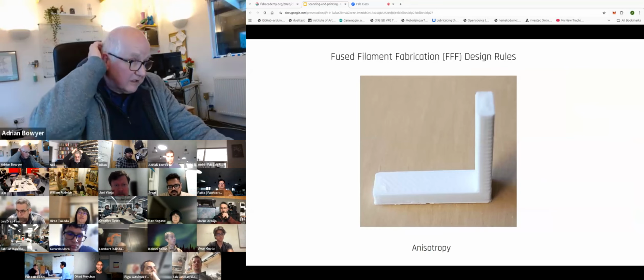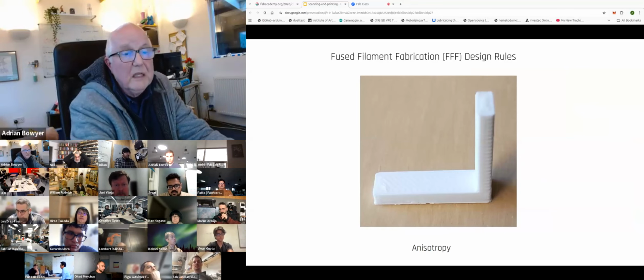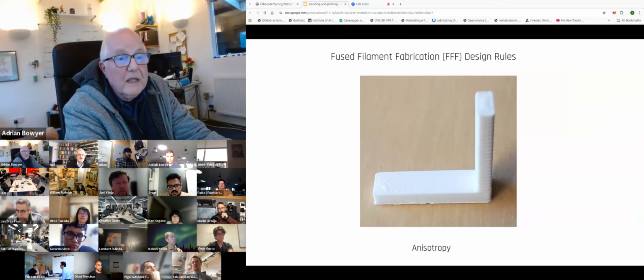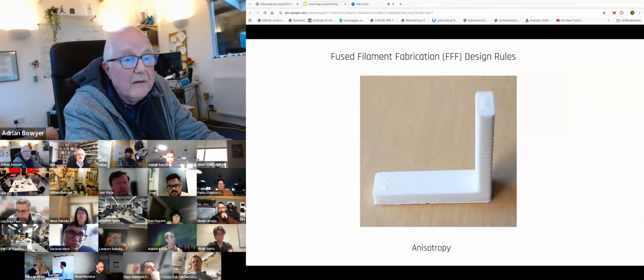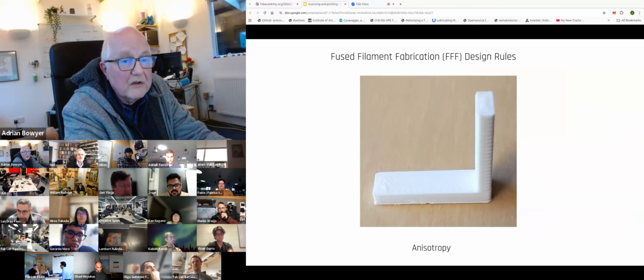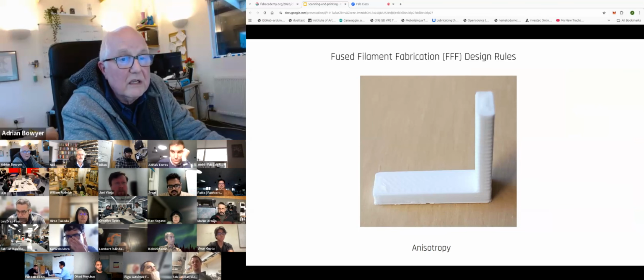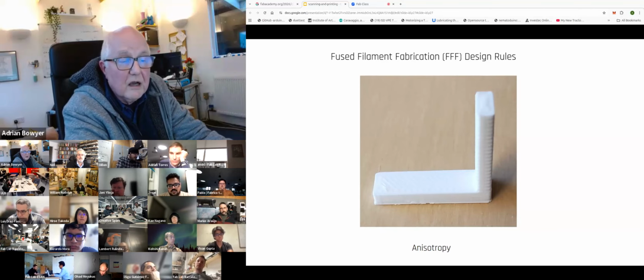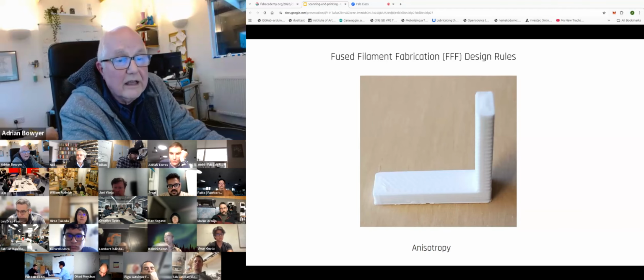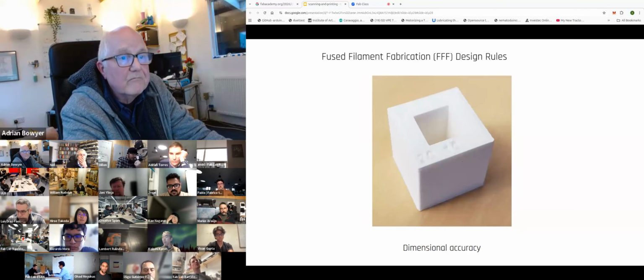Okay, another aspect to this technology is anisotropy. We're printing in layers. If you make this L shape, you'll find that the horizontal bit of the L is extremely strong. You probably wouldn't be able to break it with your fingers, but you probably will be able to snap the vertical, because the welding between the layers is not as strong as the plastic solidifying inner layer. So you get anisotropic mechanical properties.